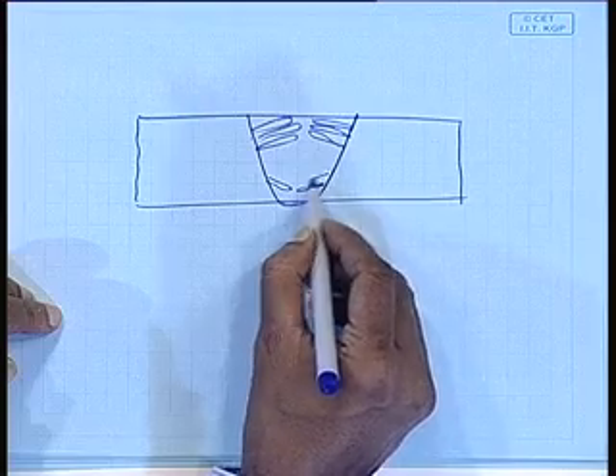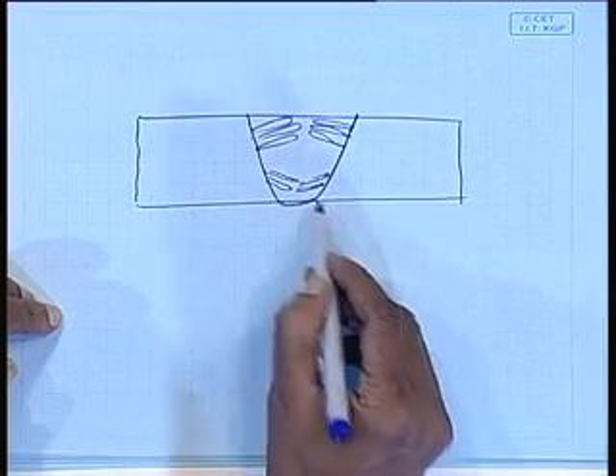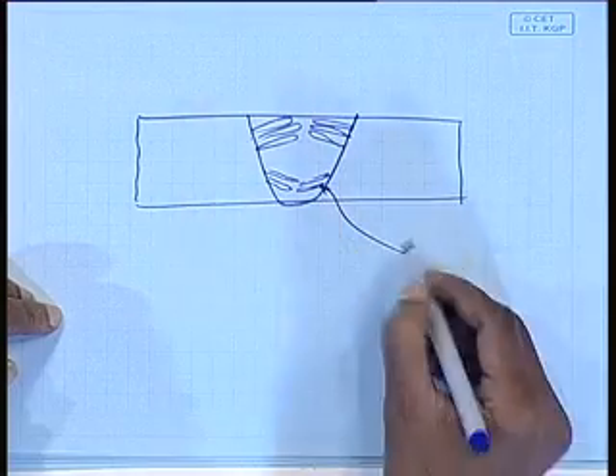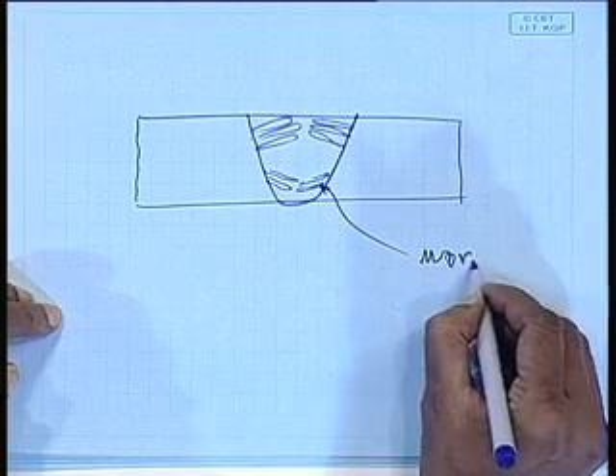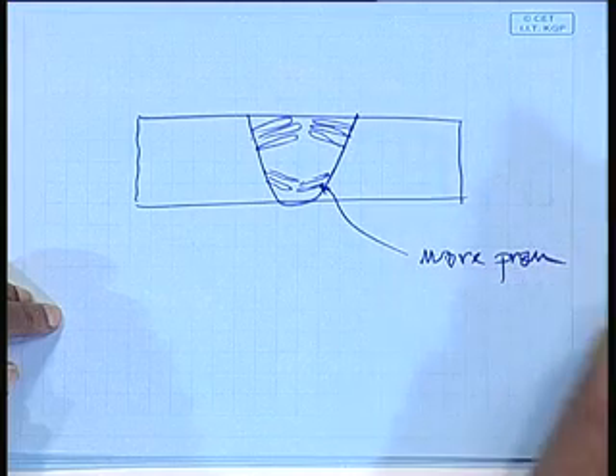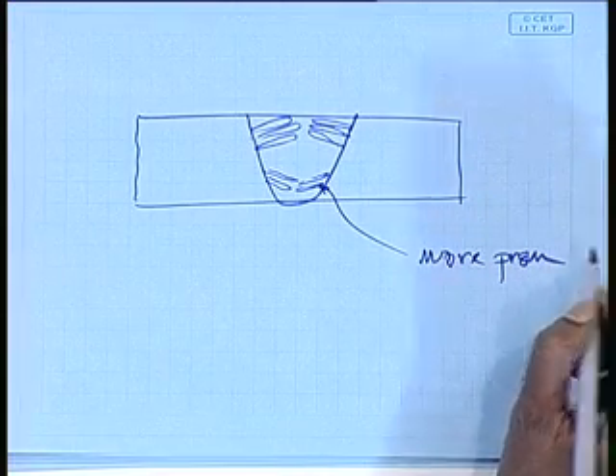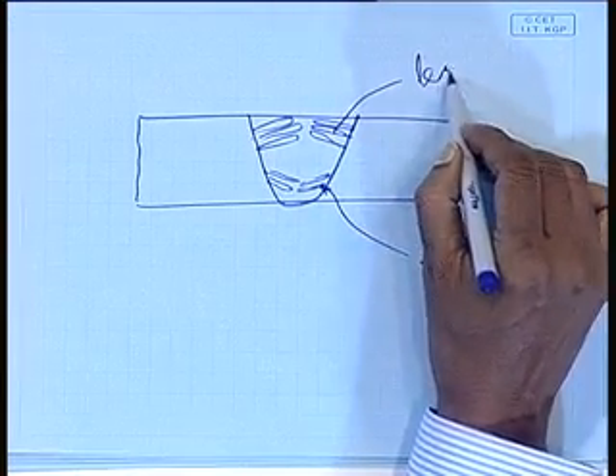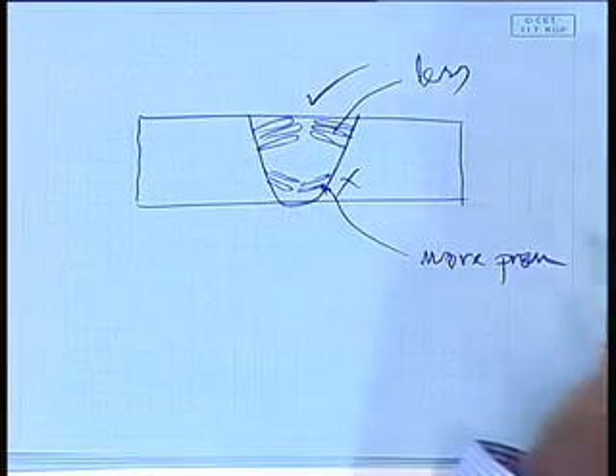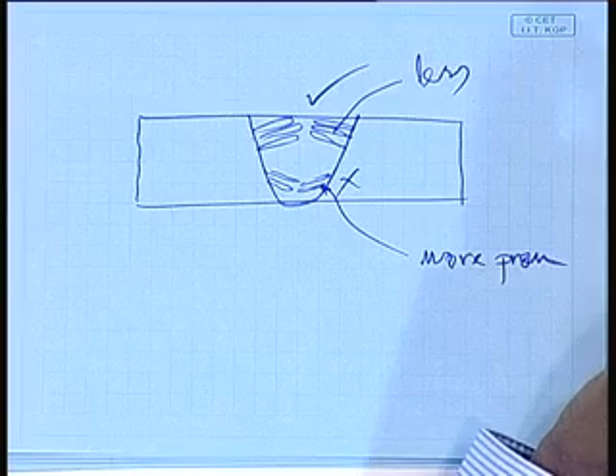If the solidification pattern is like this, then it is more prone to cracking. This is more prone to cracking, and this is less. That means this is preferable, this is not. How that happens partially depends on the composition, and also depends on the parameters, depends on the speed.